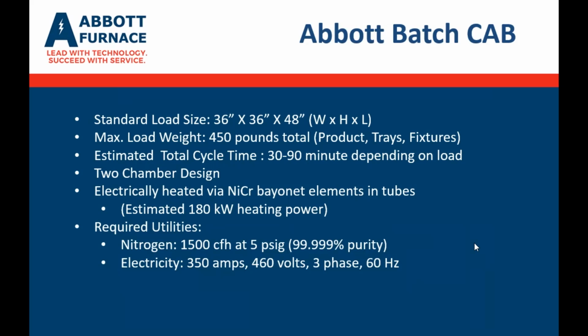That would give us a total cycle time of around 30 to 90 minutes, depending on the load mass. It's a two-chamber design, where we're using the brazing chamber as one chamber, and then a combination purge chamber and cooling chamber, which allows us the smaller footprint. In this case, we're using electrically heated bayonet elements, nickel chromium, in protection tubes to protect them from the atmosphere. At that 450 pound total, the design calls for about 180 kW heating power. For the standard utilities, nitrogen consumption would be about 1500 CFH at the purity levels that we spoke about, and then it is run on electricity and can be tailored to whatever your local requirements are.